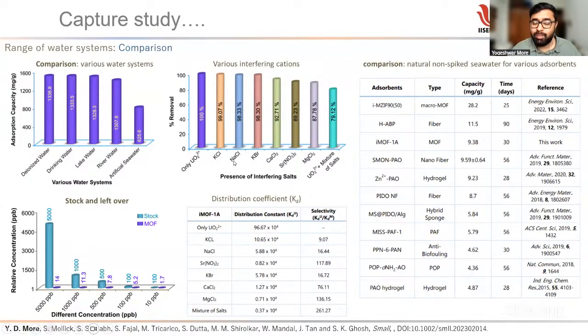Whereas potassium and sodium dominate because they are present in higher amounts in seawater. So if you compare a unit volume of seawater, one uranium ion has to compete with 40,000 sodium ions. That is the ratio in seawater to the other ions. And if sodium is 40,000 times higher, you need an adsorbent which is very selective and reusable.